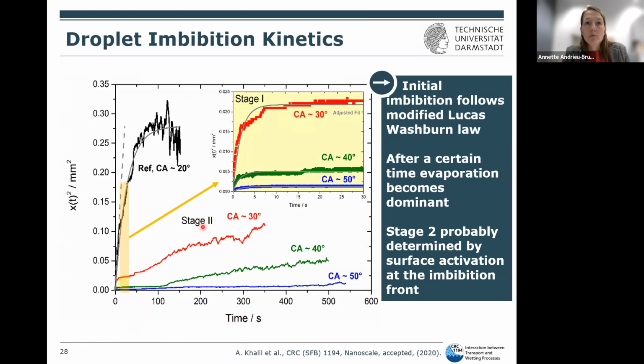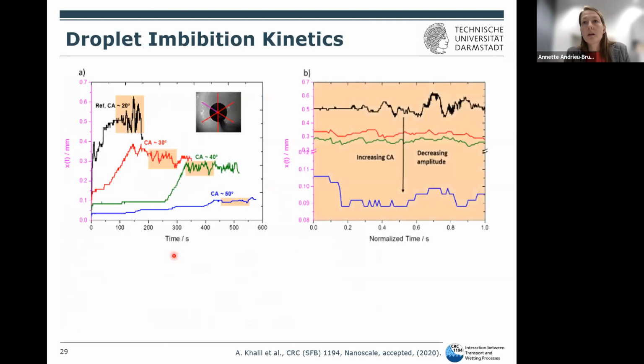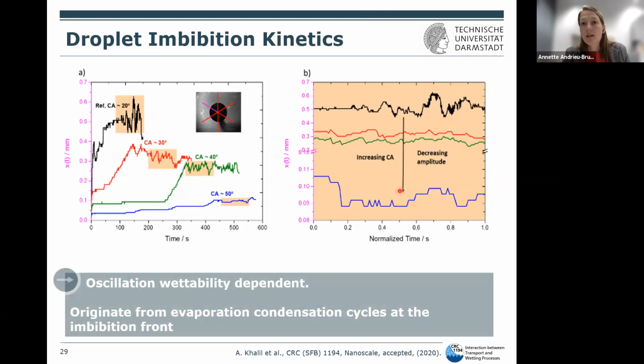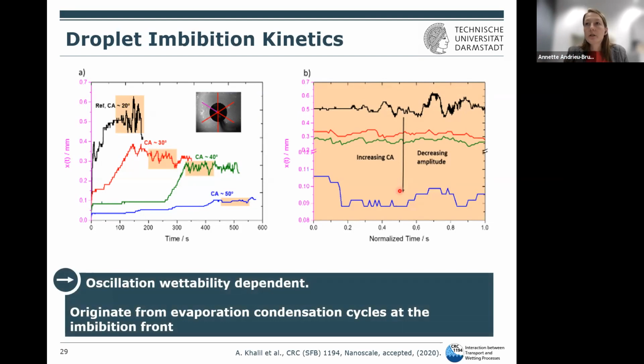What we observe now in functionalized pores is that here again, the fluid front often starts to move again. We are not yet sure what the exact explanation is, but we assume that this is a kind of activation at the imbibition front due to these condensation processes. But I cannot exactly state right now what exactly causes this effect. Yeah, this is again just the zooming into this oscillation, and you also see that the amplitude of this oscillation decreases with increasing contact angle, and this again makes sense if you remember the water adsorption curves and the capillary condensation and its dependence on the contact angle. So as well, this oscillation is wettability dependent.